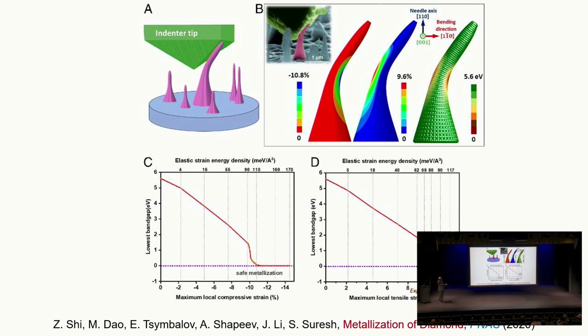This is the tensile strain. So on this side, you have the tensile strain, and the tensile strain is as high as 9.6%, and you have compression here. If you do the same figure with band gap, both on the tension and the compression side, because band gap changes from both tension and compression, this is what you get. For the same amount of deformation of the bent diamond nanoneedle, you can get a band gap that approaches, if not quite 0, it approaches 0 on either side.